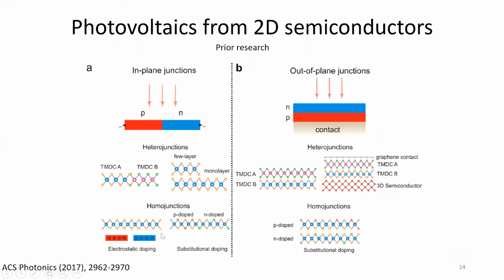Because they are atomically thin in nature, you can use electrostatic doping to also make homo junctions, or you can actually use substitutional doping. For hetero junctions, again, people have tried different techniques, growing one on top of the other or stacking one on top of the other, which is what we do, as well as making hetero junctions with other 3D semiconductors, such as silicon or gallium arsenide or indium phosphide. And some people have also tried to do selective doping of the few top layers into p-type of naturally n-type occurring crystals to make these vertical homo junctions.